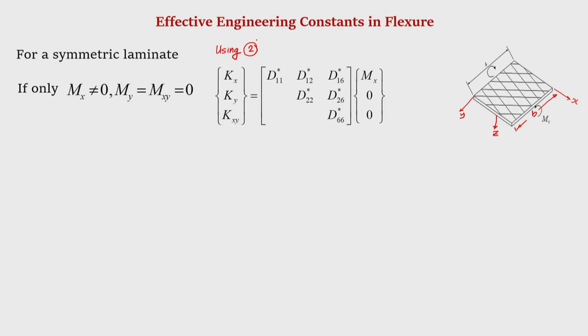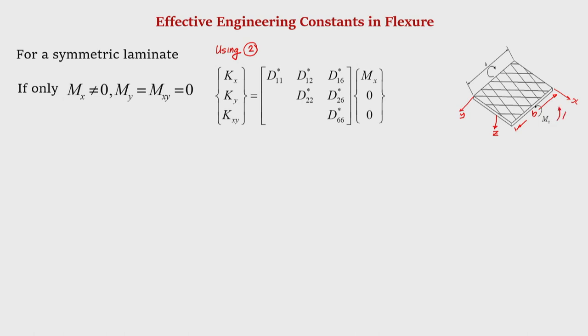In the first slide, we have written equation 1 and 2, which are the decoupled equations for in plane and the moment curvature relationship. So, if only M_x is applied, that means it is only subjected to a bending moment M_x in the xz plane, that will lead to curvature k_x is equal to D11 star M_x. Again, I am repeating, this D11 star, D12 star, these are the elements of the D inverse matrix. So, D11 star M_x, k_y is equal to D12 star M_x and k_xy is equal to D16 star M_x.